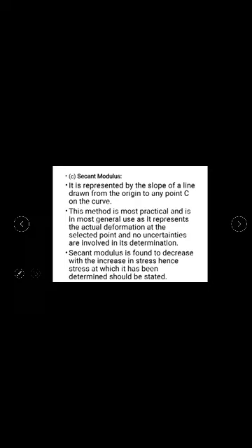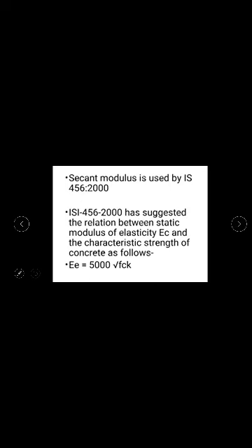Secant modulus is found to decrease with increase in stress. Hence, the stress at which it has been determined should be stated. So whenever you are telling the modulus, Young's modulus, you have to mention the corresponding stress to that modulus also, right? So secant modulus is used by IS 456 2000, Indian Standards 2000.